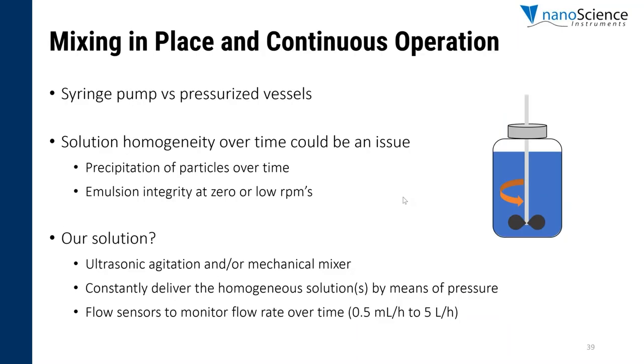This slide is about another area that a lot of people are reaching us to help them find a solution. Typical electrospinning setups involve the use of a syringe pump. When scaling up, this is not an ideal way to process a sample as the maximum volume is limited, and if the viscosity is low, you can see pulsations because the syringe pumps work through a mechanical operation. If you have an emulsion or suspended particles in solution inside a syringe, your electrospinning development will not be consistent over time, as the emulsion can de-emulsify and the particles can precipitate over time.